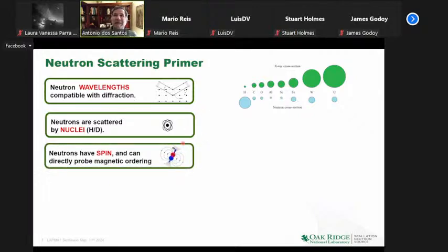Another one, which is maybe less important for society, but it's critically important for us in the LAFMAT network, is that neutrons have spin. These spins actually interact with spins in atoms, in electronic shells. The corollary of that is if the spins in the lattice become ordered because of an ordered magnetic structure, this diffraction will now reflect that magnetic ordering. So the neutron diffraction can really describe or interrogate the actual magnetic structure of materials in terms of the vectorial nature of spins with respect to the lattice orientation. So you know how each spin is oriented at each location of the lattice with respect to the lattice. And that is a truly unique technique that, as far as I know, no other techniques give that level of detail.